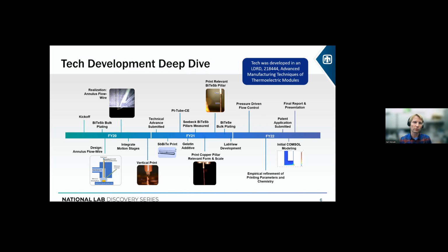The thermoelectrics were ternary materials, so bismuth, tellurium, antimony, and bismuth, tellurium, selenium, so our N and our P-type materials, and we were able to grow those columns into pillars, and those pillars are part of a thermal pile for a thermoelectric device. The LDRD wrapped up in about FY22 with a patent application submitted and final presentations, and the technical readiness at the end of this program was around a 3.5 or so.